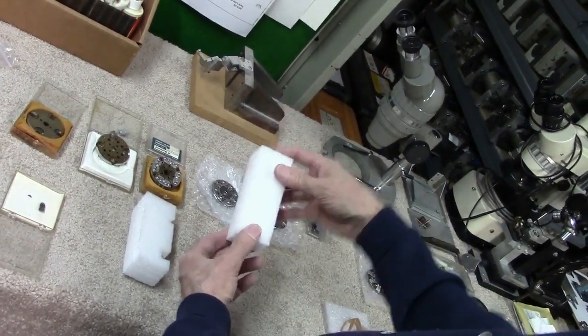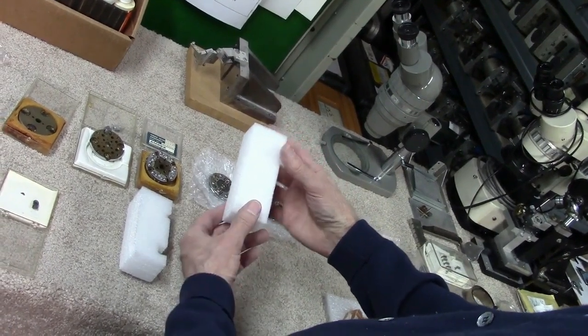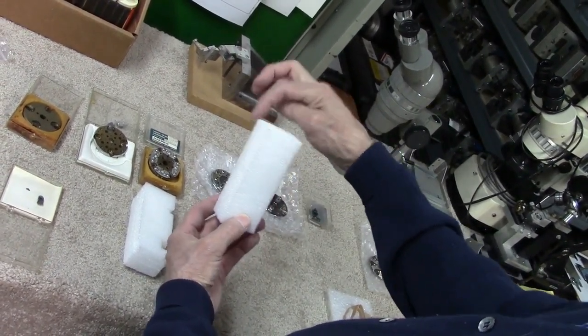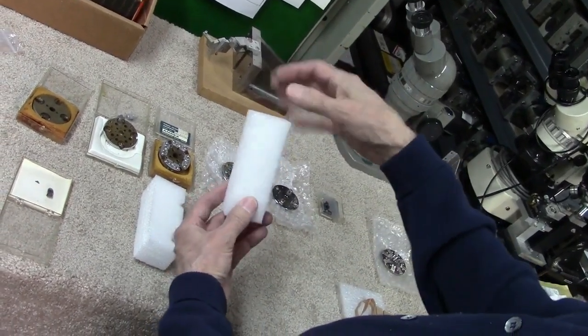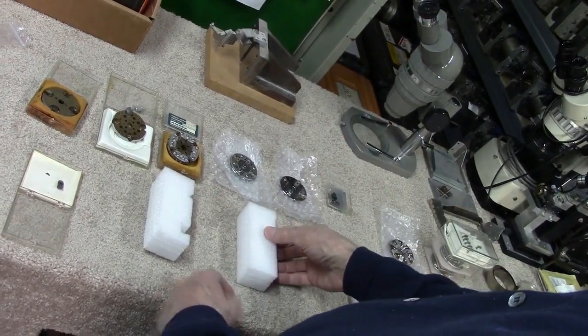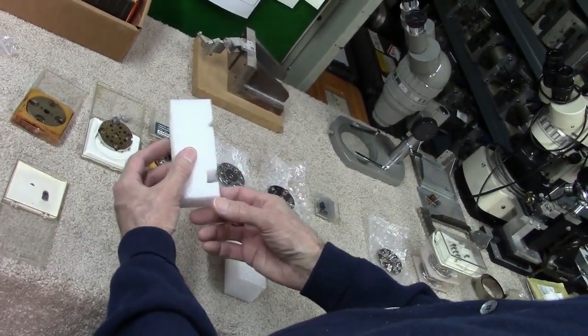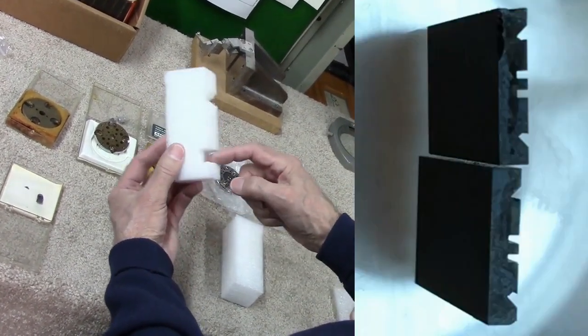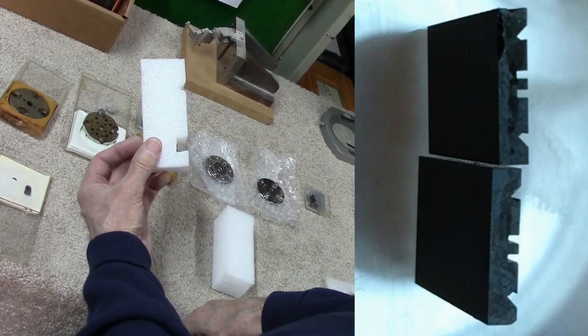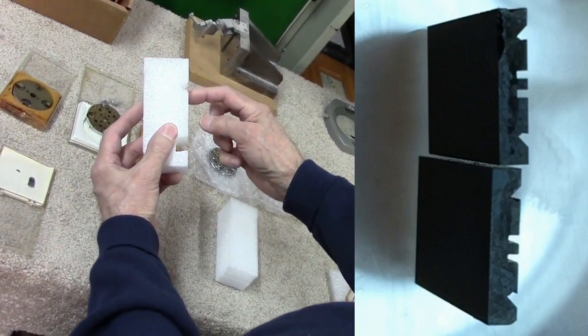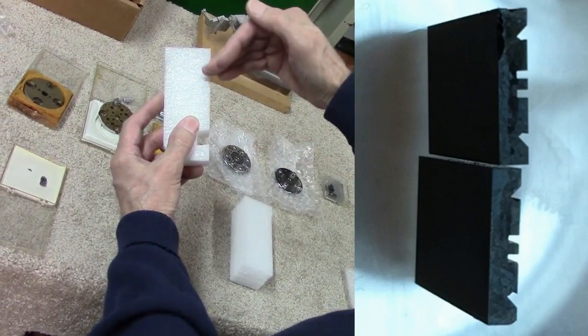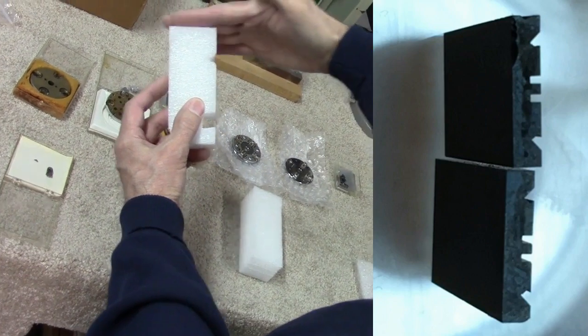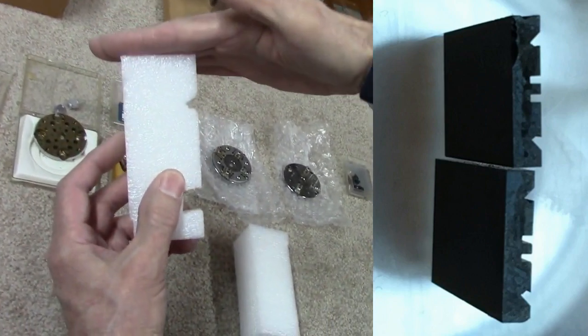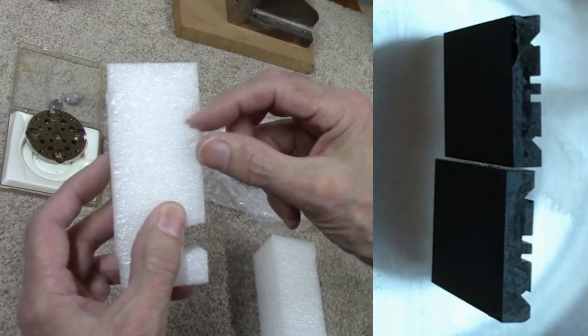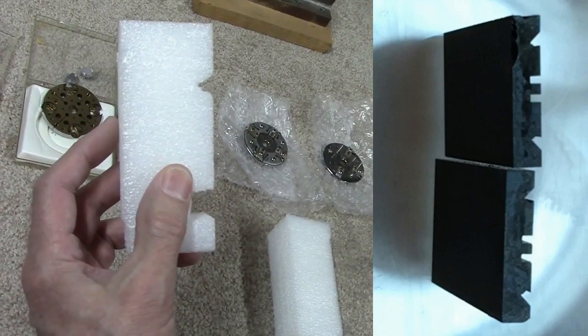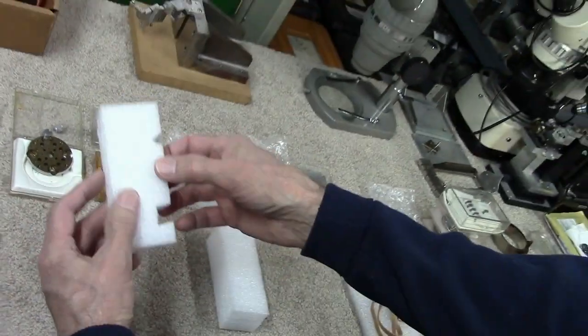So we have a rectangular block, and this would be about 3/10 of an inch square and about 1/2 inch long. And same here, same dimension. Into this block we would grind a little U channel, and then here we would have a channel ground on a 45-degree angle to this plane here. So this would be 0 and that would be 45. Kind of like a V-looking notch.